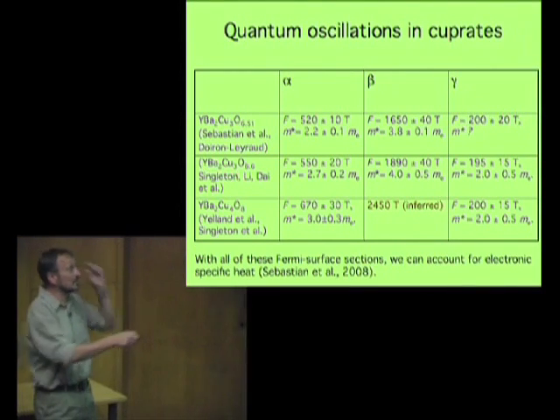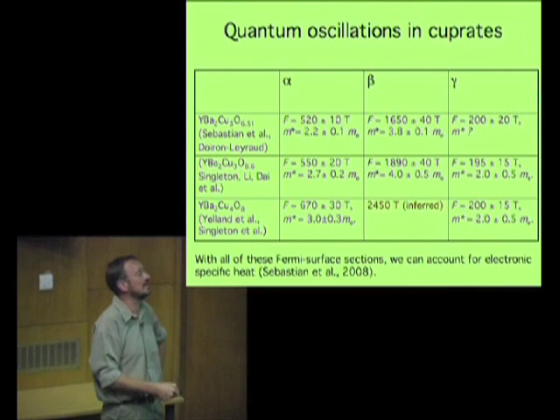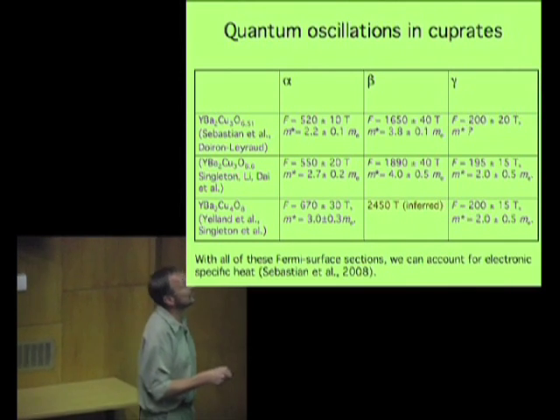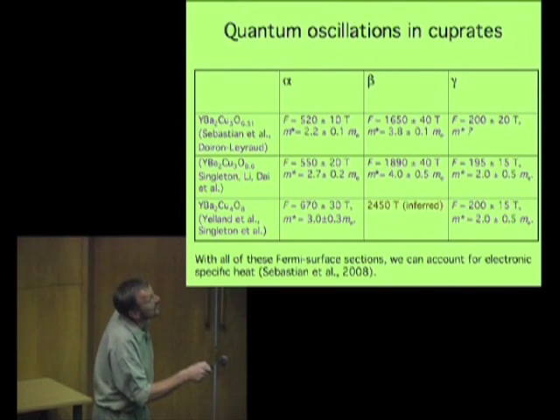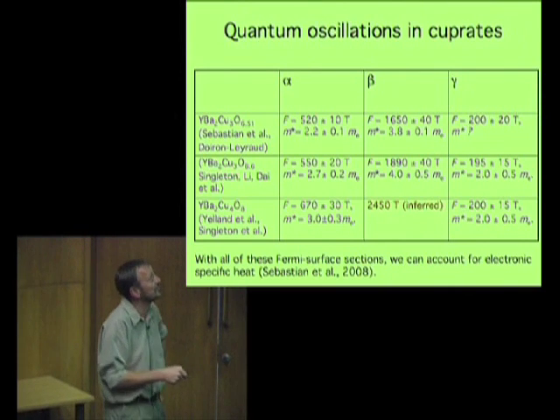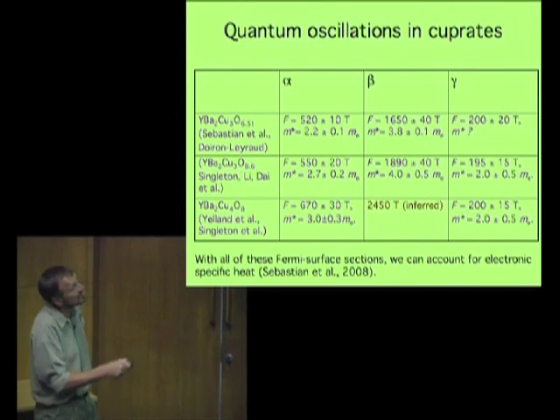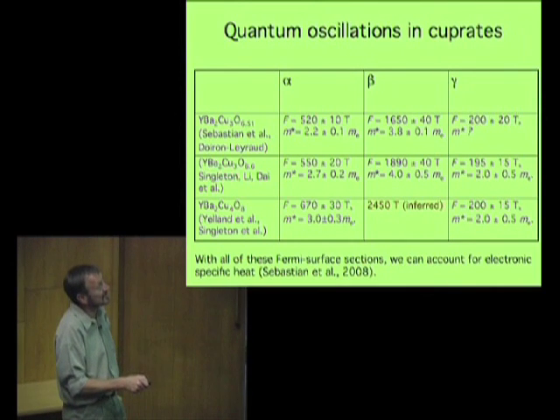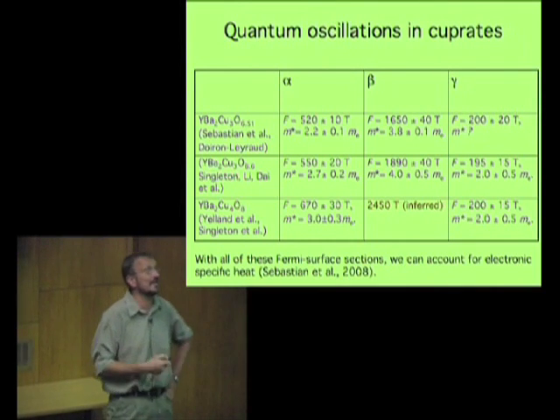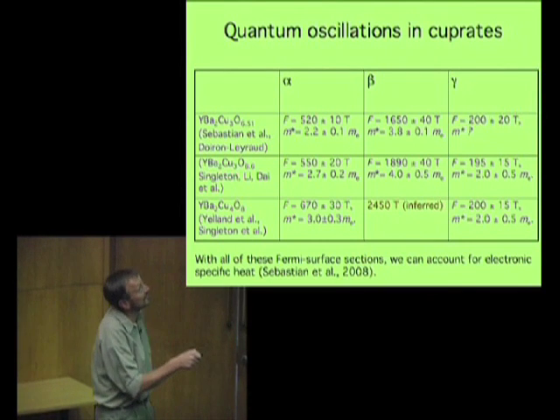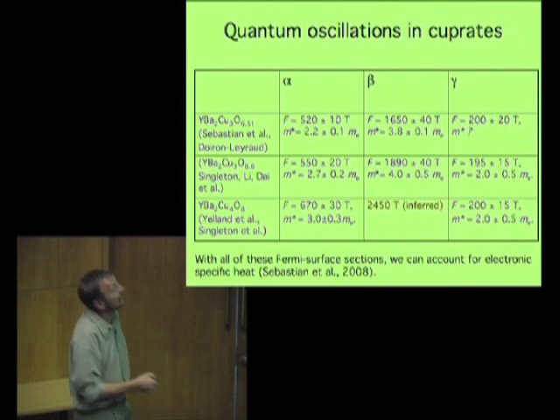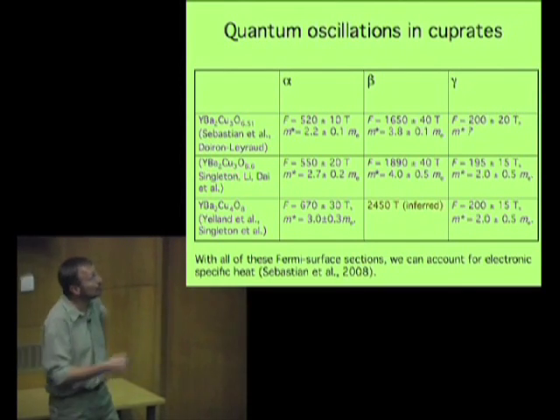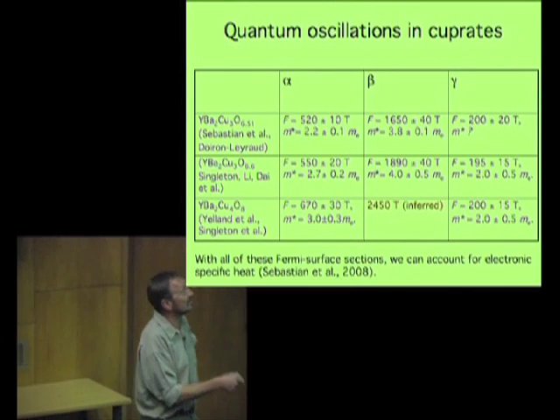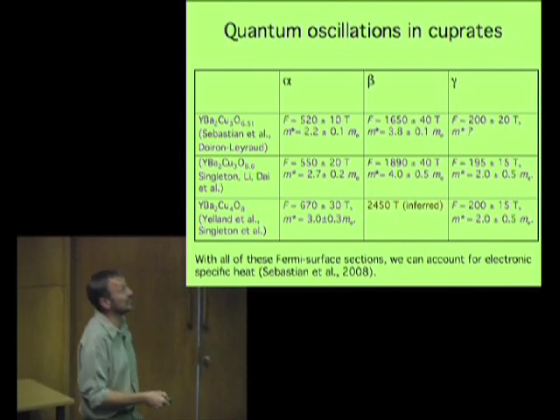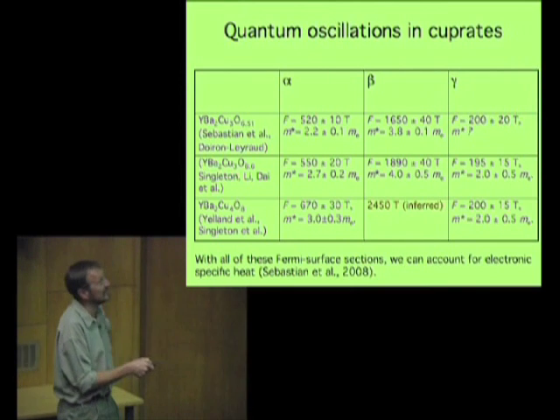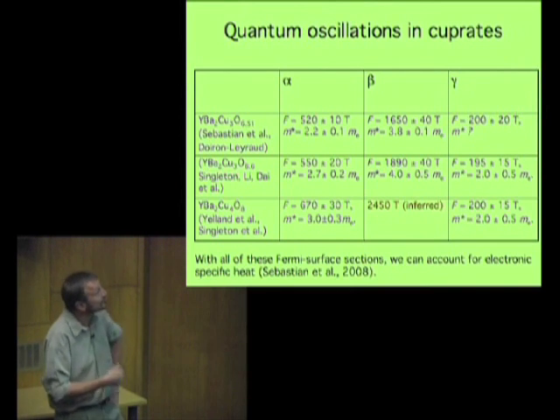Now, why is this important, this high frequency, which produces very weak oscillations? The reason is that it's got heavy effective masses and it's got a large area. And if you include this one, we can account successfully for the electronic specific heat of these cuprates. By counting these three sections of Fermi surface, we have enough holes to deal with the electronic contribution to the specific heat of the cuprates. So in other words, we think we've detected everything there is to detect.